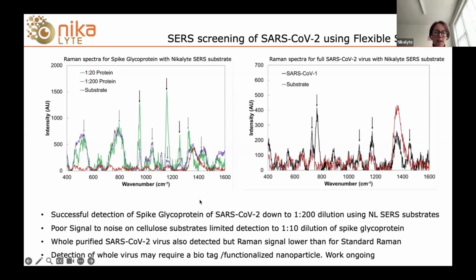I haven't put the data here, but actually the cellulose substrate also was able to detect, but only down to 1 to 10 dilution. And the reason for that was that the peaks basically became lost in the noise, which is another example of where colloidal chemical SERS substrates are less sensitive than the gas phase substrates of Nikalyte. So that was a very encouraging result.